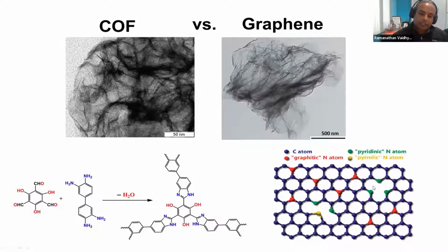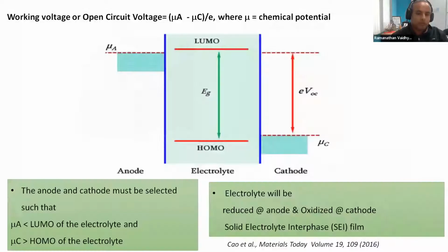So if you want to dope nitrogen into graphene, typically you take a carbonaceous source like a paper or a textile, and you pyrolyze a nitrogen-rich small molecule, and then you get doping, which is going to be very random. And also you do not know what kind of chemical nitrogens are buried in your structure. Whereas in comparison, if you take a COF, you are going to form a stoichiometric combination of monomers, and you are going to get a very ordered structure, which means you know exactly the nature of your heteroatom, and also they are distributed in a very periodic fashion, which means their axis and site specificity is going to be very high. And this really excites us to look into COFs as a very interesting material.